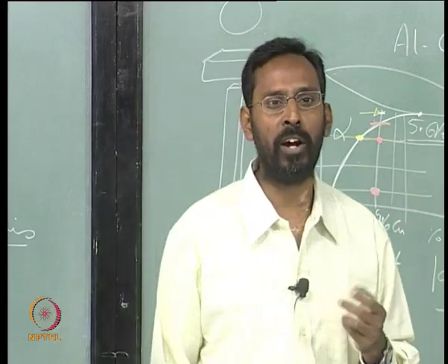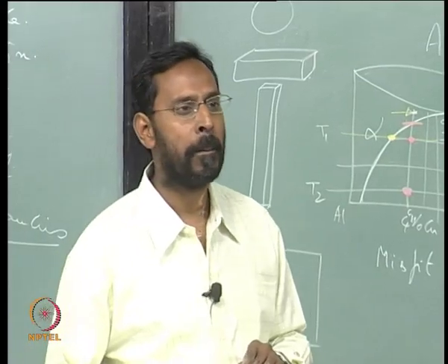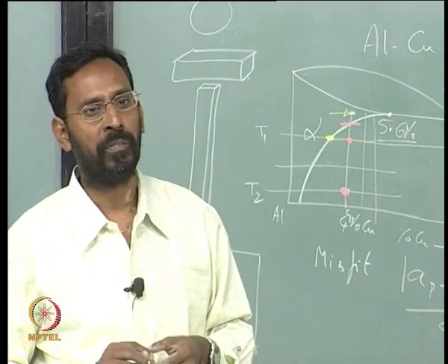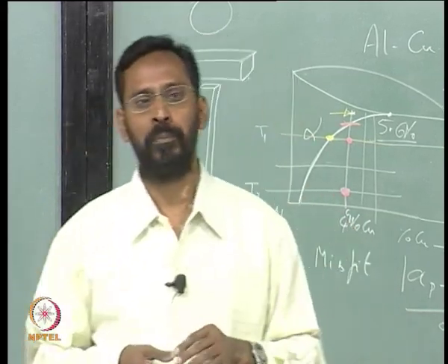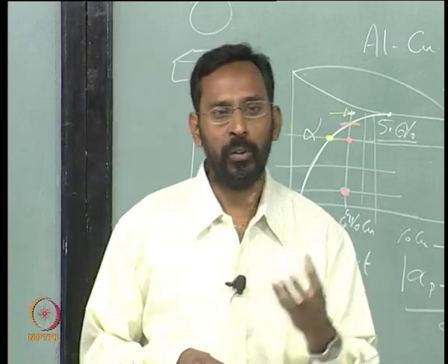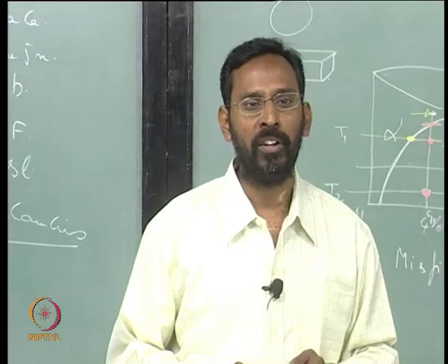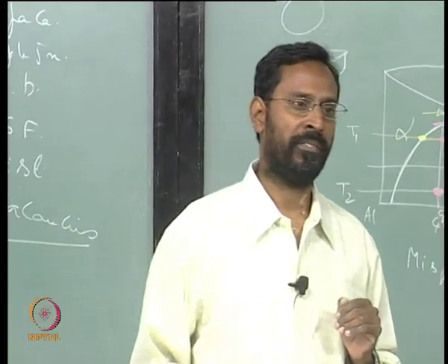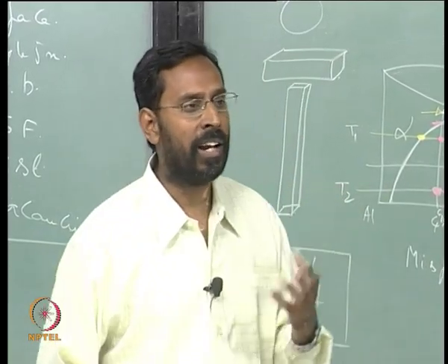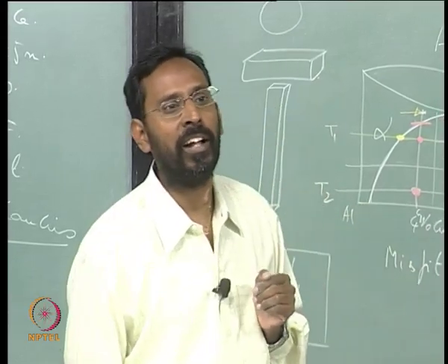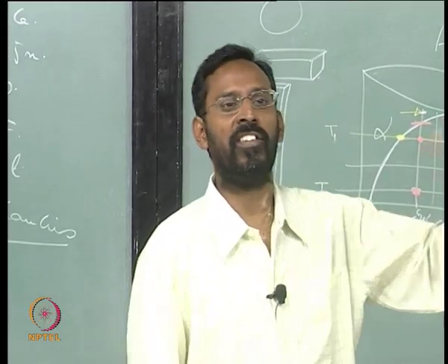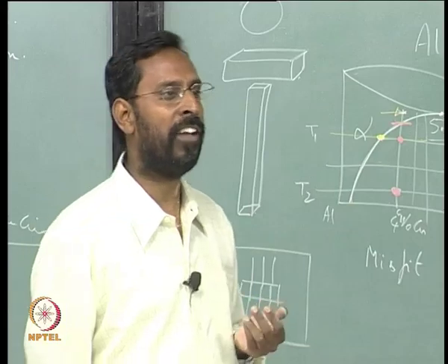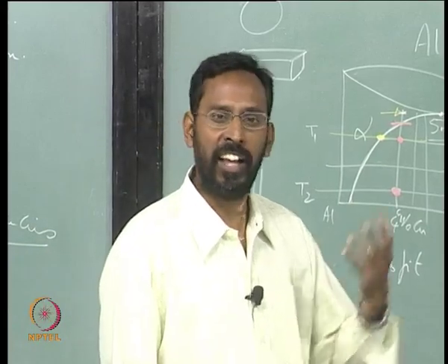Are you aware of any system where you have spherical precipitates? Any solid state transformations where you get spherical precipitates? Gamma gamma prime. Ni3Al, when it nucleates inside the nickel based matrix, you always see spherical precipitates initially, and when they grow they become cuboidal. Similarly, aluminum lithium phase diagram, Al3Li precipitates inside the aluminum, again spherical. Aluminum silver phase diagram, you have a phase called Al2Ag, again spherical.